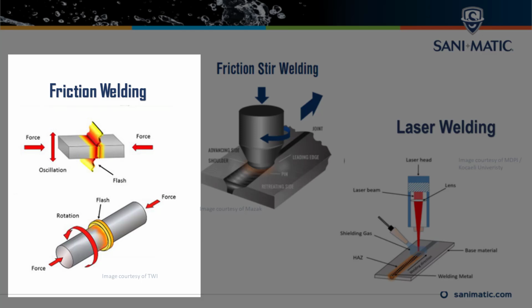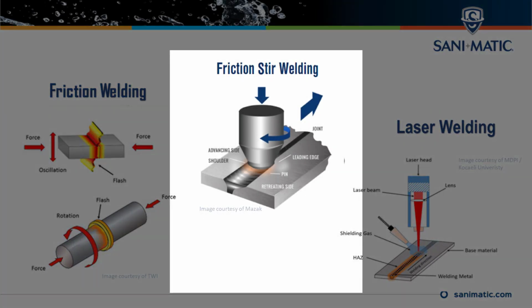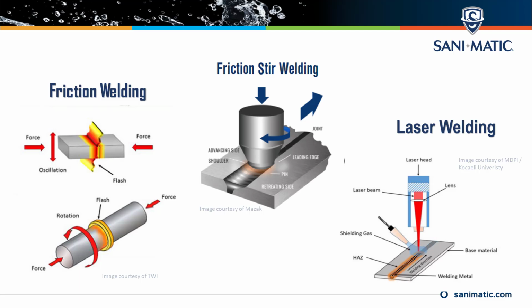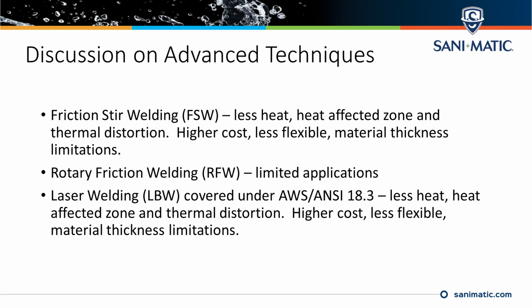Stainless probably works very well for this because it tends to gall very quickly. Friction stir welding is where you actually are spinning a head on a mill, and that head is causing friction, as we kind of see here, and it's actually welding the two plates together by the heat and friction created from that head spinning. Of those three, some interesting things about that: on all three of these, the heat affected zone is less. So we talked about corrosion caused by heat affected zone. We talked about that a little bit yesterday. I'll go into that maybe a little bit more in depth.